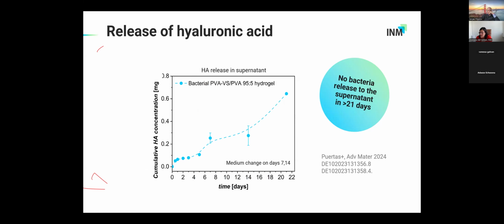Now, does this lens really release hyaluronic acid? This is our target. And you see here that it does work. This is a contact lens, as I showed you before, a hydrogel containing a bacterial hydrogel, which we have incubated in medium over several days, actually 2 weeks, and we have measured in the supernatant if hyaluronic acid is produced. You see that hyaluronic acid is produced continually up to at least 21 days. And within this material, with this composition, we see no release of bacteria. So the matrix is also providing the biocontainment we need.